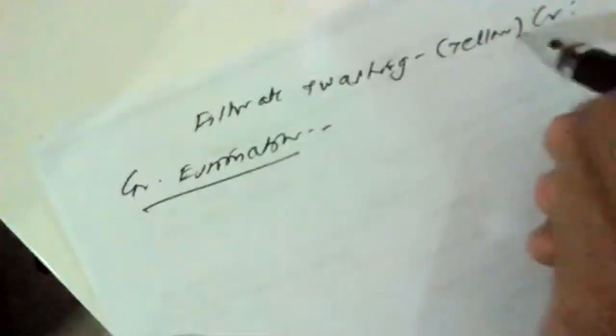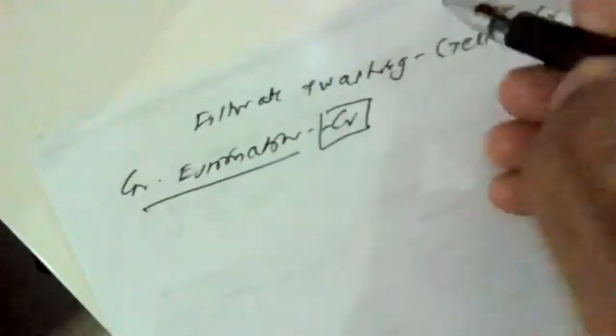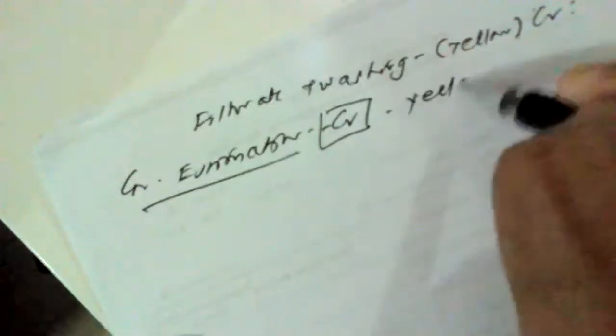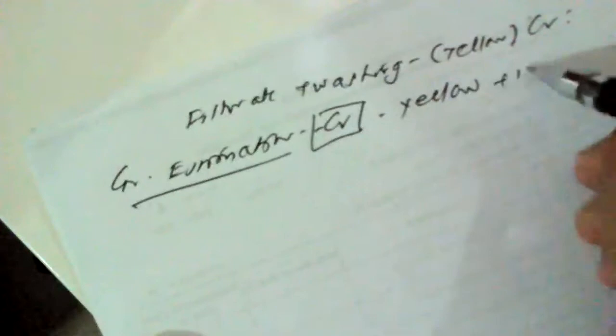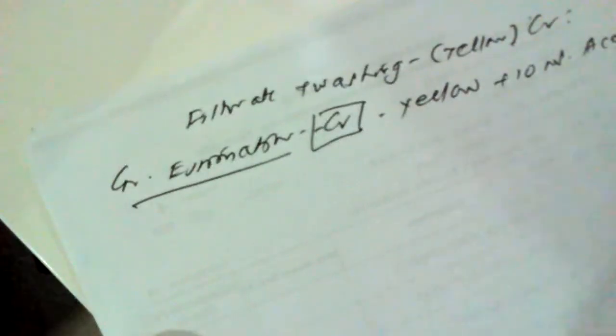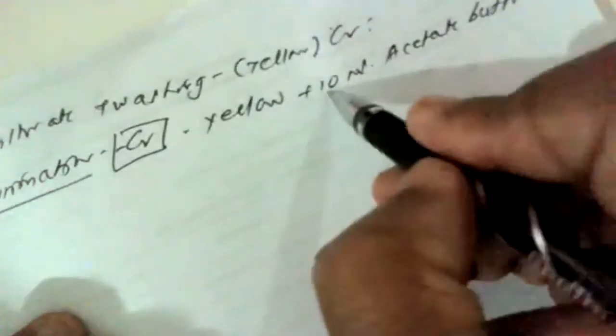So, for the gravimetric estimation of chromium, the yellow filtrate we have to treat. To this yellow filtrate, we have to add 10 ml of acetate buffer, which is an already prepared solution. You are not expected to prepare it. We have to add just 10 ml of this acetate buffer solution to the yellow filtrate. Then we have to add around 40 ml of 4% solution of lead nitrate, Pb(NO3)2.